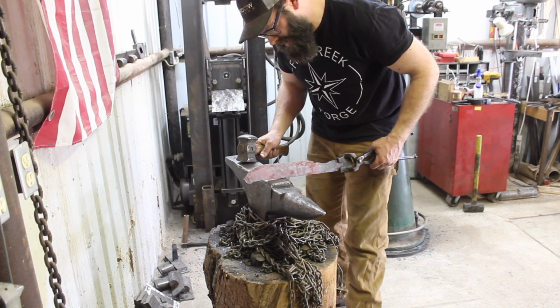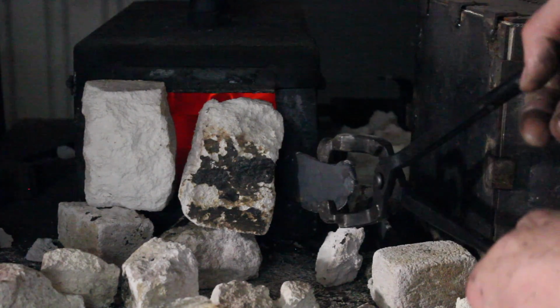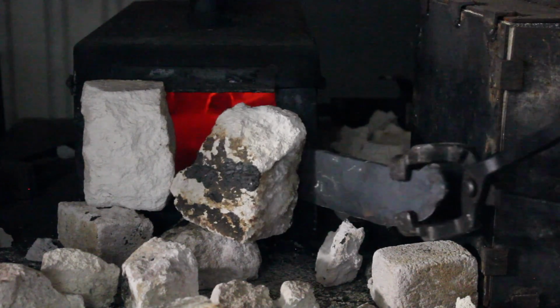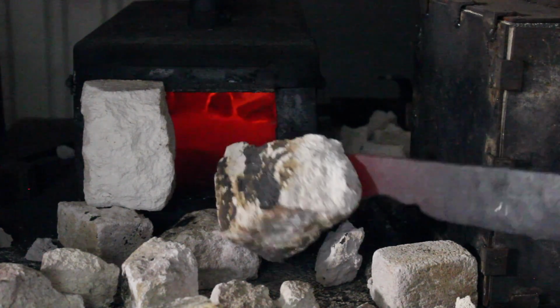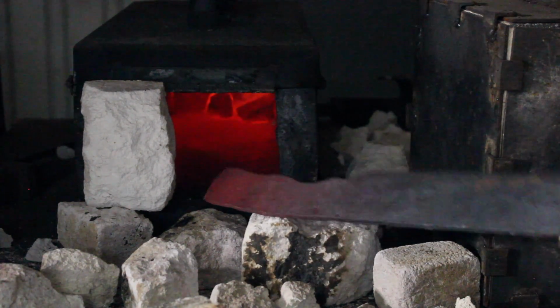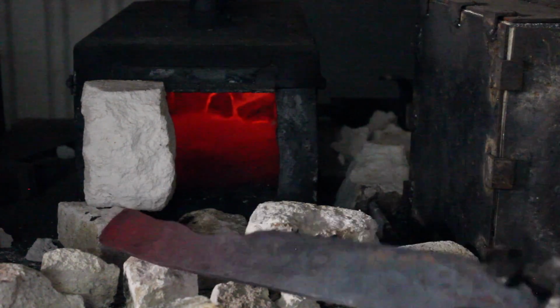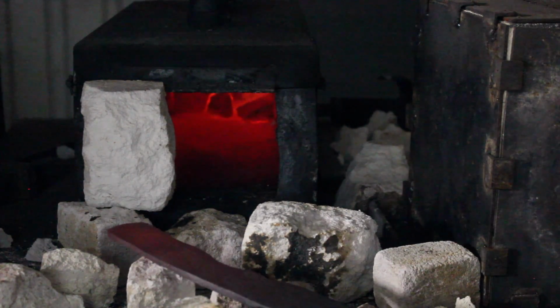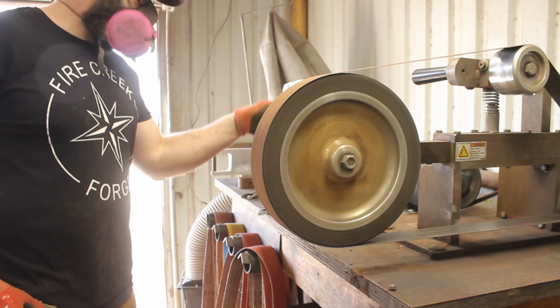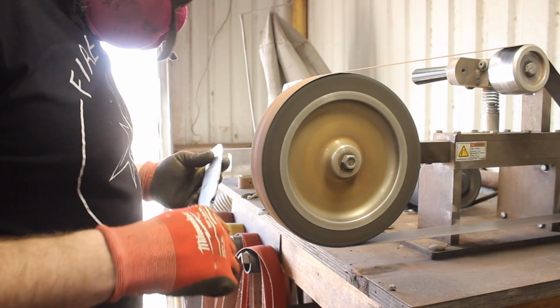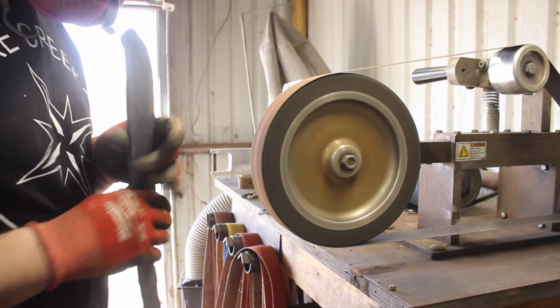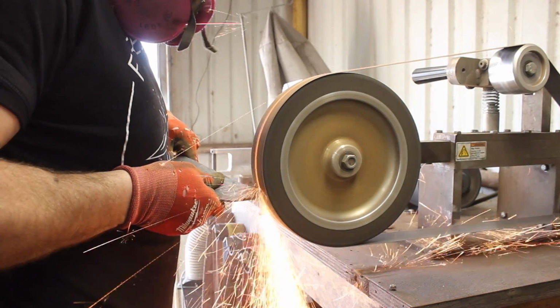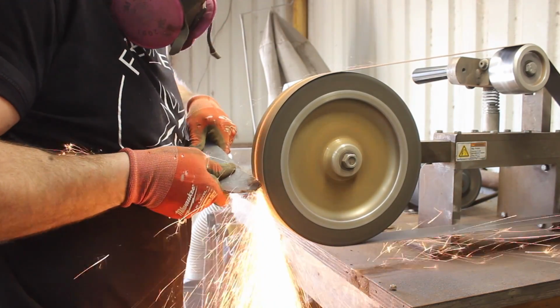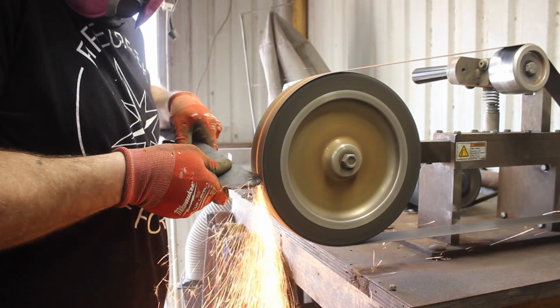So that's important. You saw me pulling out of the forge there at a dull or low red heat, almost not visible. What I was doing there was heating it up to a dull red and letting it sit there for a little while. That's just a quick, simple spheroidizing process on the tang, which is going to allow us to get our bolt holes drilled in the handle without issue.